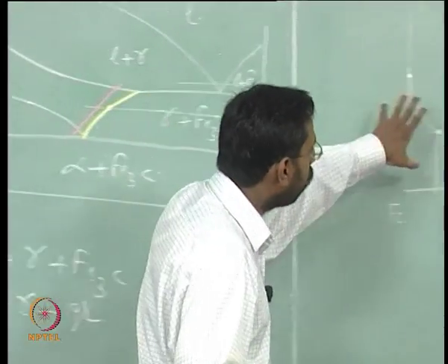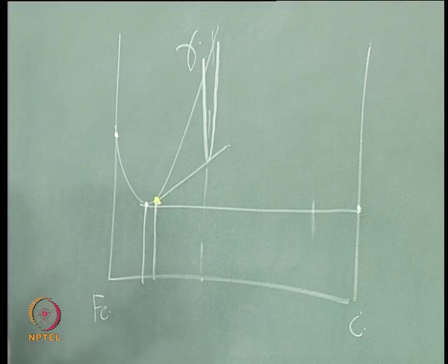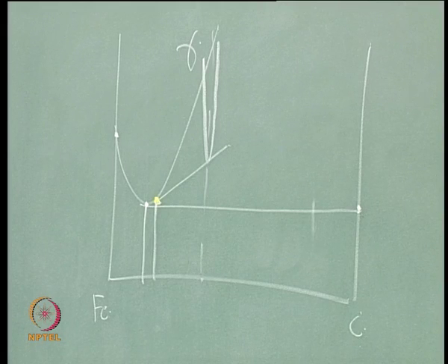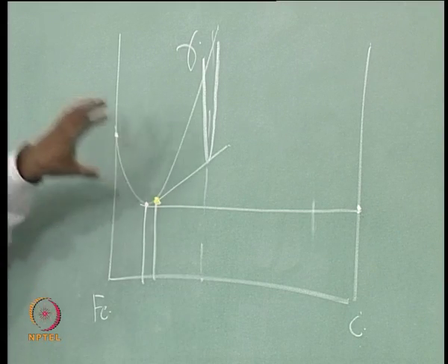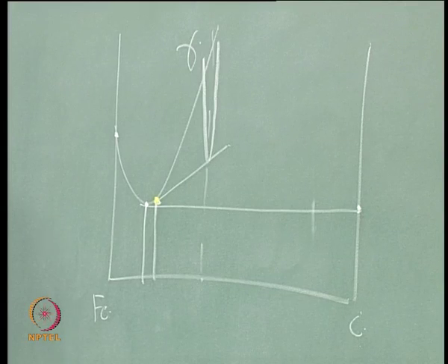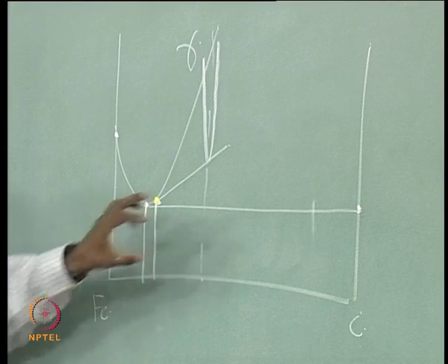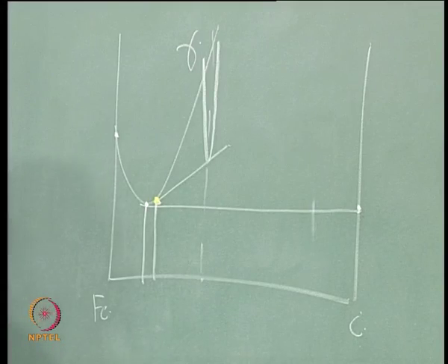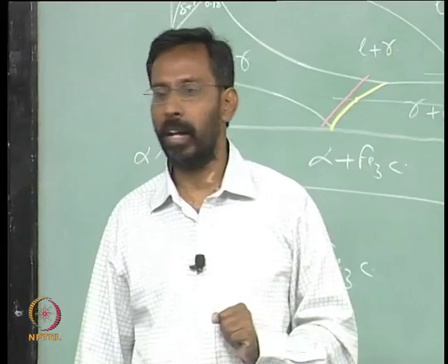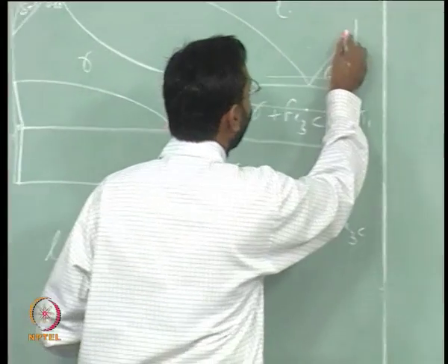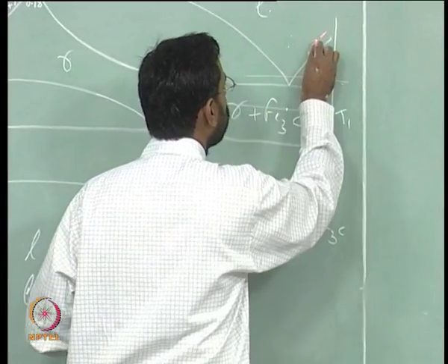So, these curves, these common tangents are not going to really get affected. The exact positions will get affected, but the relative positions are never going to be affected. The relative position always tells that the composition of any phase, liquid or gamma or alpha, in equilibrium with graphite will always have a lower carbon content when compared to in equilibrium with the cementite. If that is the case, then I will see that this will be